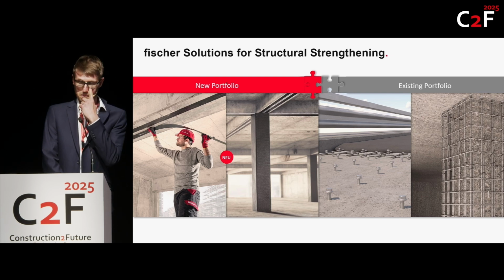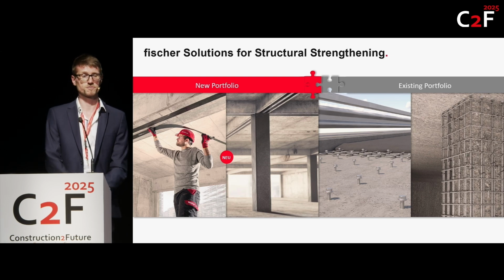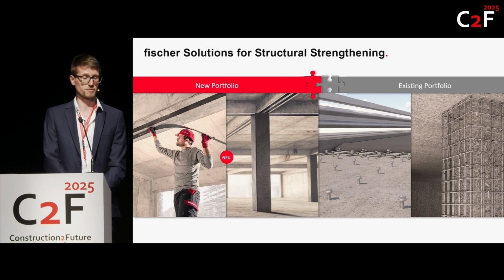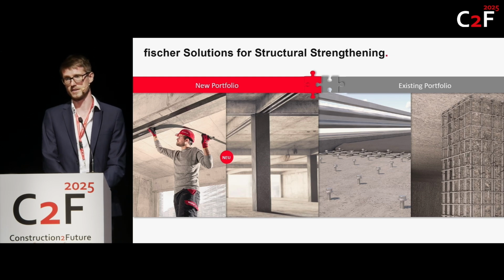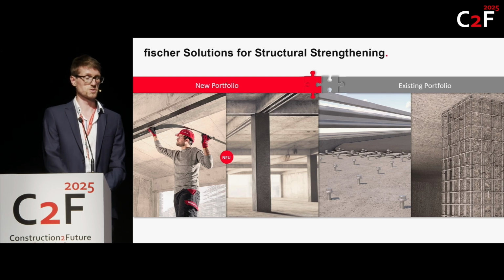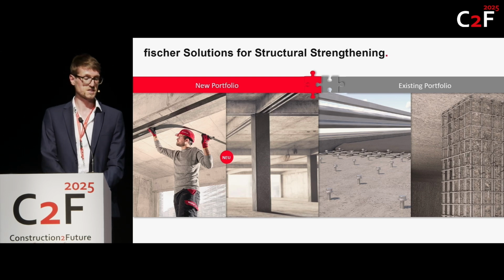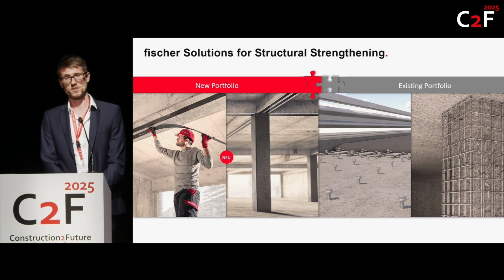If you want a parking garage to be retrofitted, most often they do it in 48 hours. They want to reopen in 48 hours. If you do it with concrete, you have to wait 28 days until your concrete is cured. So it needed to be fast, so we went with epoxies. It needs to be durable. We wanted to not increase the dead load of existing structures.